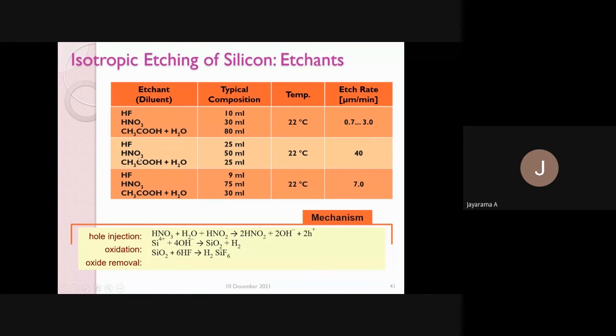Whereas here the composition is different - the etch rate is 40, same composition type but different amounts. The composition here is HF 25 ml, HNO3 50 ml, acetic acid 25 ml. That means 4:2:... no, 1:2:1. This is 1:3:8, or you can find the ratio.